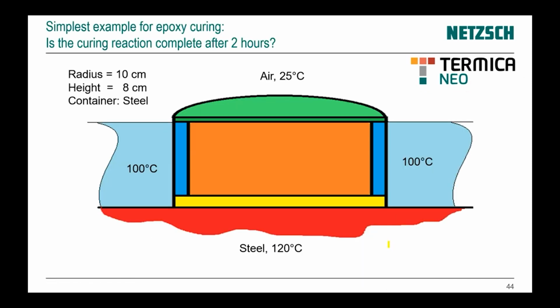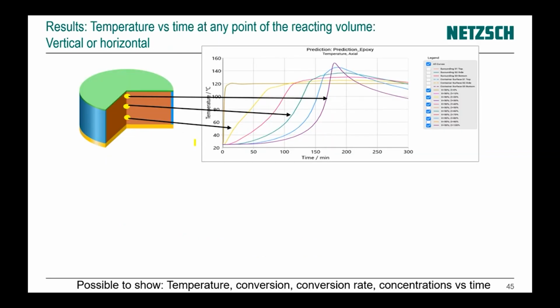We can have some geometry, with a different temperature from different sides. We can have a different material on the different sides with different thermal conductivities. We can use different container values, or for example, some substrate on the bottom. And this substrate can have a different material which is selected from the library, and we can also select the thickness of this material, and after that we can make a calculation.